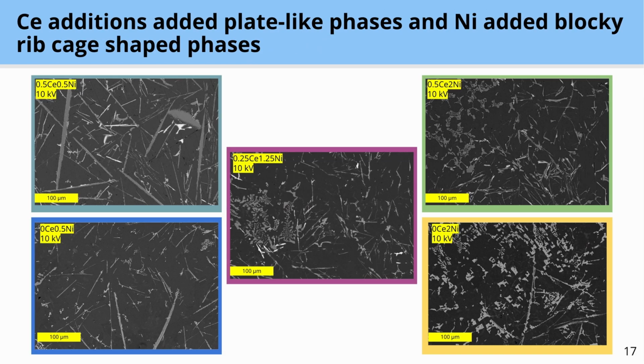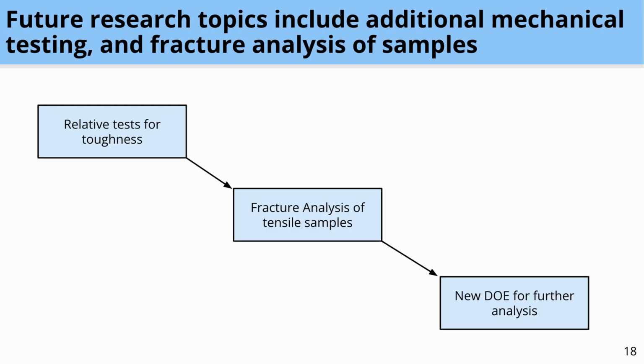Additionally, we did SEM, which is scanning electron microscopy, to determine what the composition of the phases were in the alloy's microstructure. And from that, we saw that cerium additions added plate-like phases and nickel added blocky ribcage-shaped phases. In the future, for this project, we plan on doing additional mechanical testing and plan on doing fracture analysis of our tensile samples. From those results, we plan on developing a new DOE for further analysis.